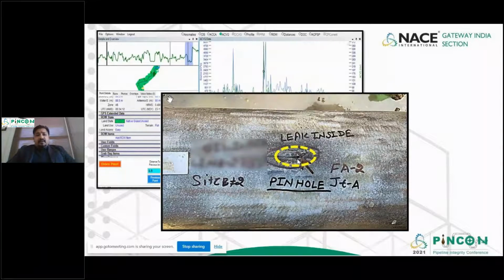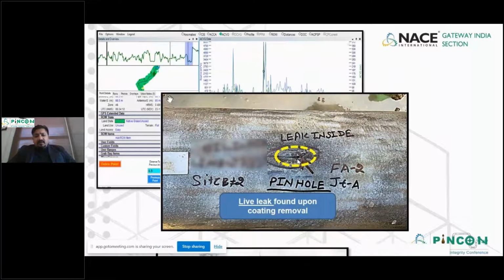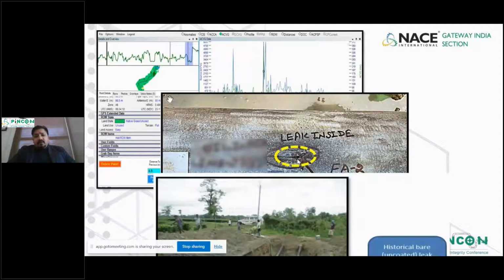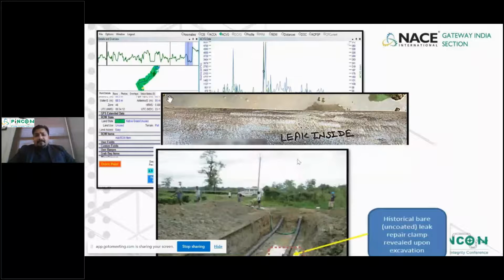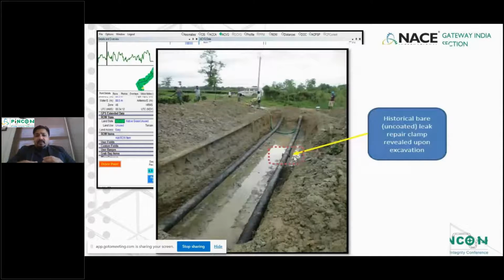In another location, we find we have caught an indication which was flagged as a coating anomaly by ACVG. But of course, when you do the excavation, we see that it was not exactly a coating anomaly. It was a coal tar coated pipeline, and a clamp on which there was a leak before. The client had repaired the leak using a clamp, and the clamp was left bare. Therefore, our technology, the machine that we had deployed, saw that bare clamp as an indication which got flagged during our data assessment, and therefore could catch it.